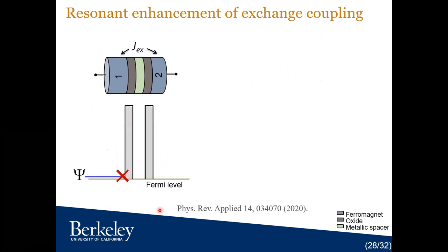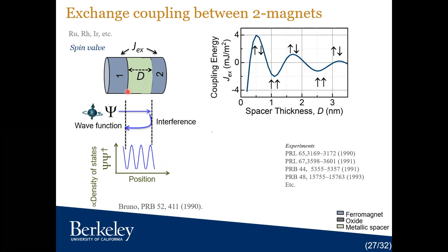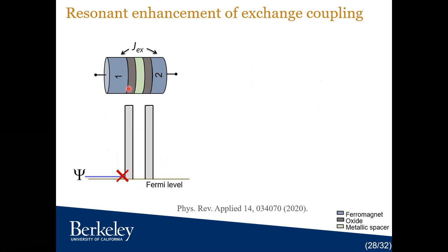So what we are proposing is to engineer this phenomenon into a device. We added two oxide layers. When you have large oxide layers, you have large barriers. So the wave function cannot travel from left to right anymore because a large barrier diminishes it. But since you have two barriers with a metallic layer in between, if you choose the right materials, you can create a quantum well in between with discrete energy states.